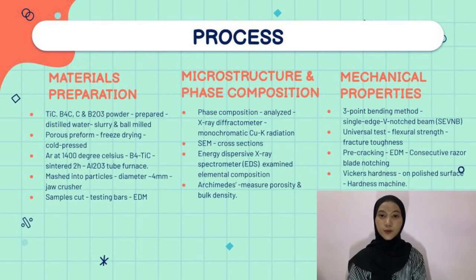Thirdly, the mechanical properties. The 3-point bending method and single-edge V-notch beam (SEVNB) method were used on a universal testing machine to determine the flexural strength and fracture toughness. Next, for the SEVNB test, pre-cracking in samples was performed by EDM and consecutive razor blade notching with 1 micrometer. Vickers hardness is also measured on the polished surface of the samples by a hardness machine.